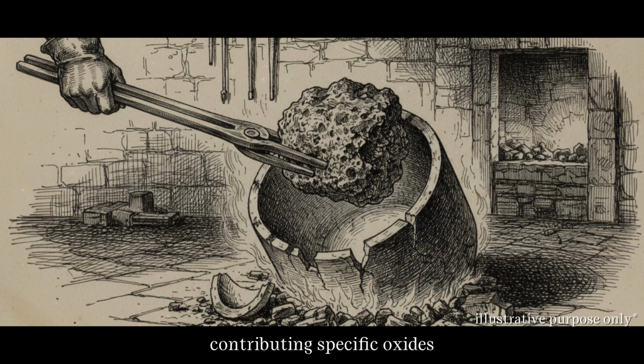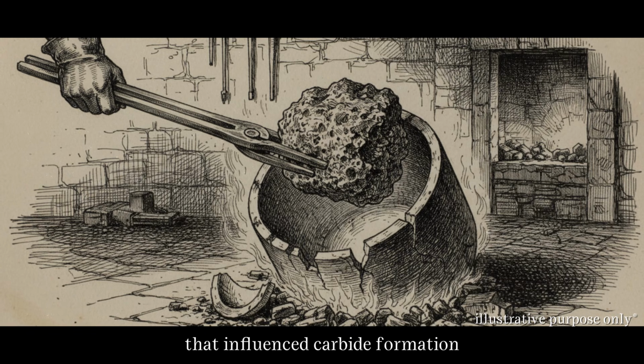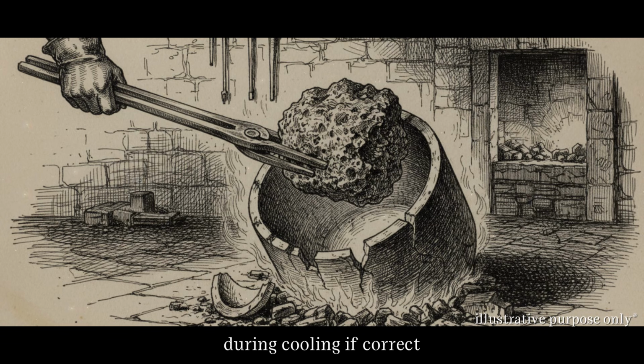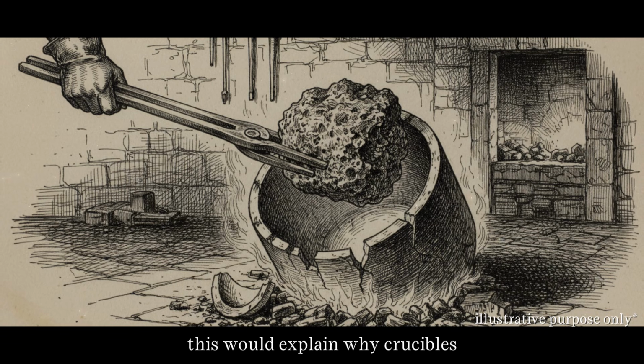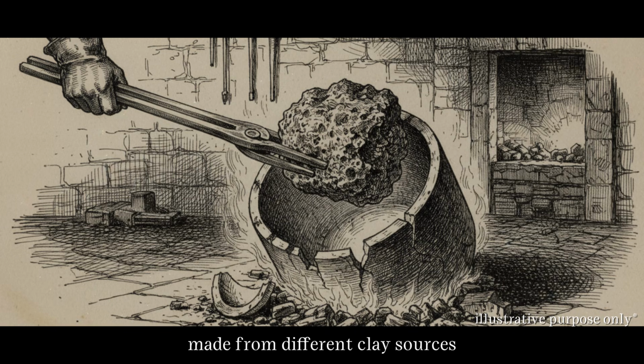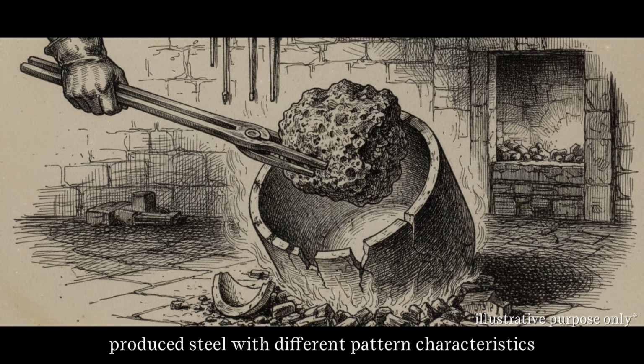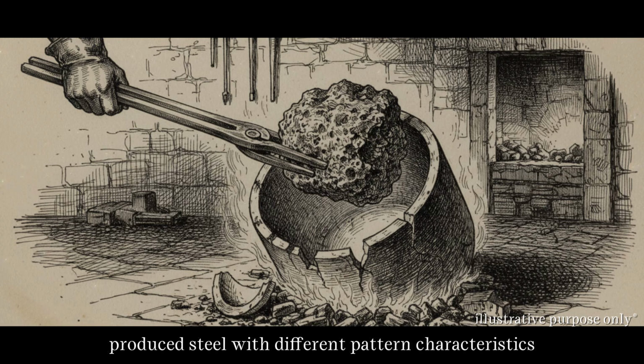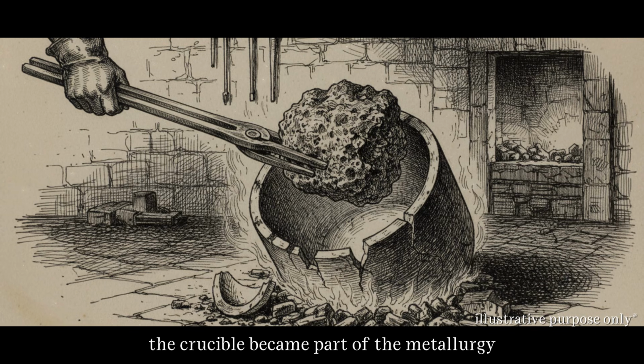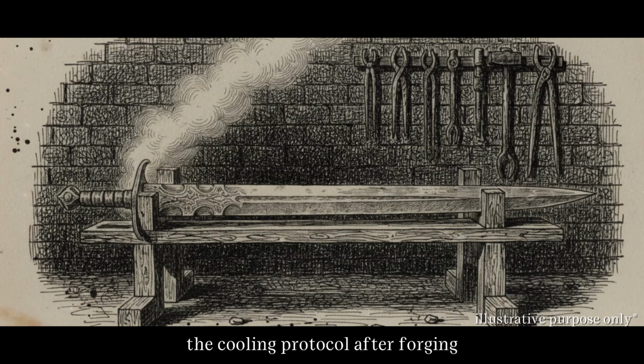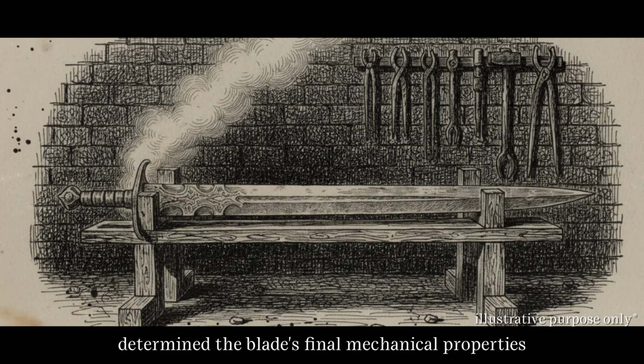contributing specific oxides that influenced carbide formation during cooling. If correct, this would explain why crucibles made from different clay sources produced steel with different pattern characteristics. The crucible became part of the metallurgy. The cooling protocol after forging determined the blade's final mechanical properties.